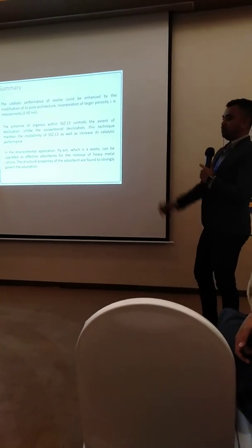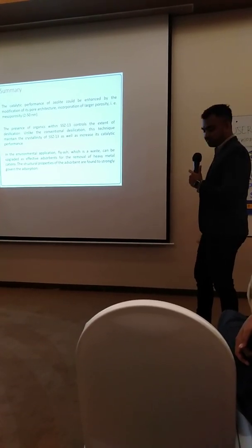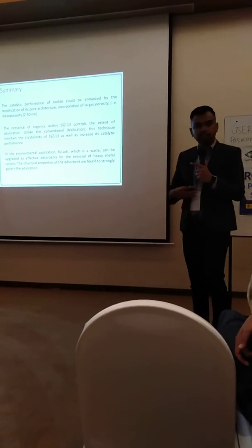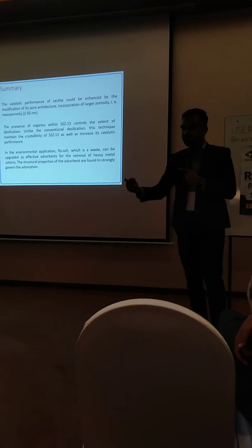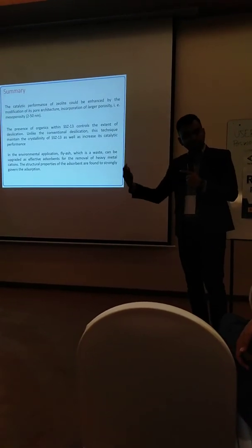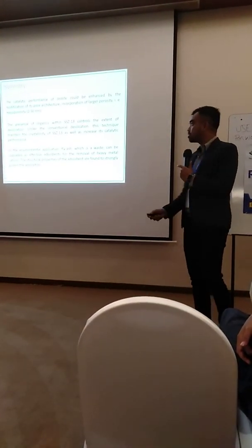So in summary, the catalytic performance of zeolite can be enhanced by modification of its pore structure, by introducing larger porosity. It can be mesoporosity of 2 to 50 nanometers, or it can also be macroporosity higher than 50 nanometers.